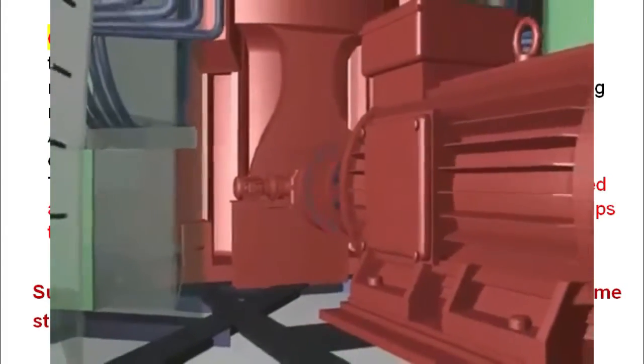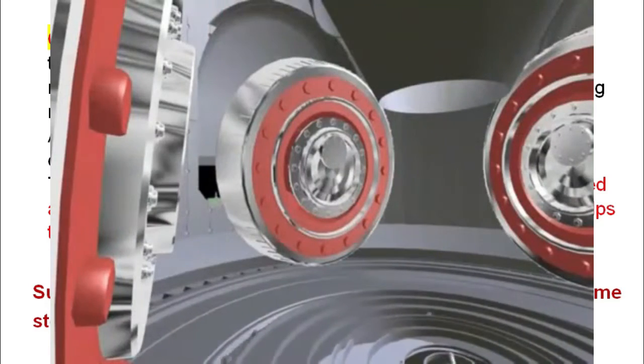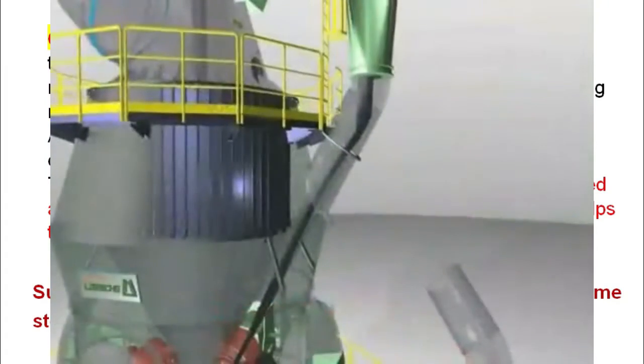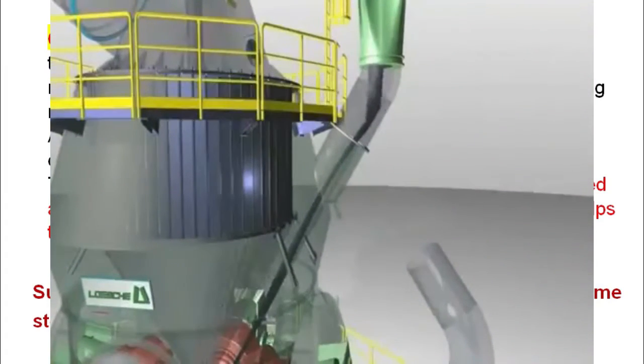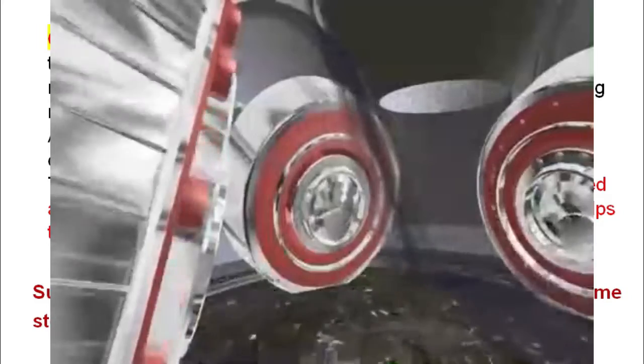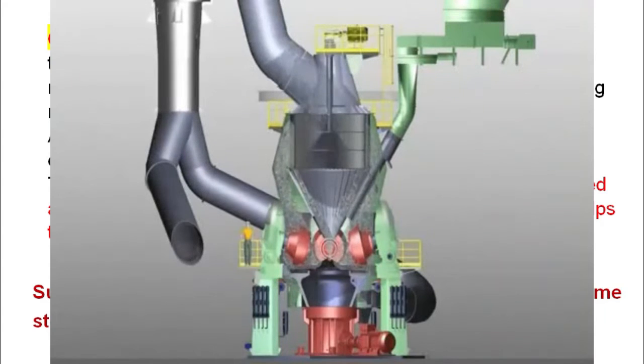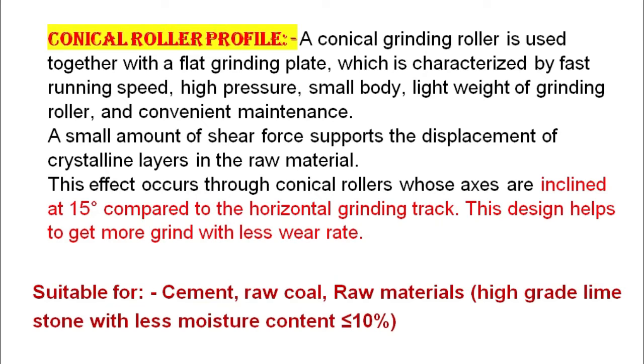Let us see the advantages of this roller. The conical grinding roller is used together with a flat grinding plate, which is characterized by fast running speed, high pressure, small body, light weight of grinding roller, and convenient maintenance. A small amount of shear force supports the displacement of crystalline layers in the raw material. This effect occurs through conical rollers whose axes are inclined 15 degrees compared to the horizontal grinding track. This design helps to get more grinding with less wear rate. This is a very big advantage. This type of roller is suitable for cement, raw coal, and raw material with high grade limestone with less moisture, less than or equal to 10% moisture.